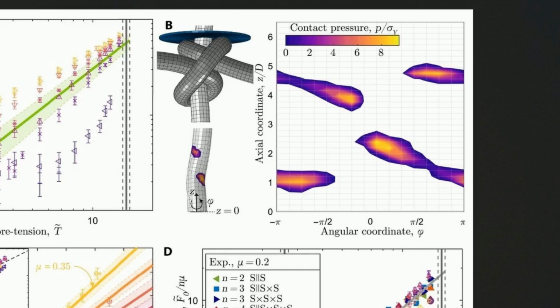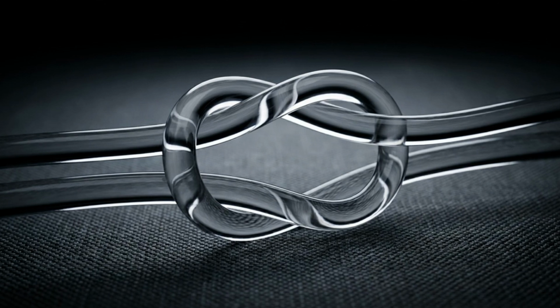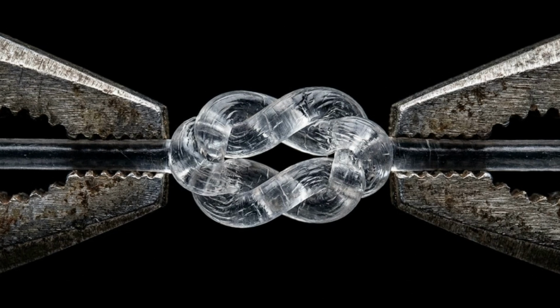This three-dimensional contact pressure map proves the result. The bright high-value areas in panel B show that where the strands overlap, they create immense, highly concentrated pressure points. This geometry turns a uniform polymer into a highly stressed structure, and at this point, the material is primed for damage the moment we add friction.